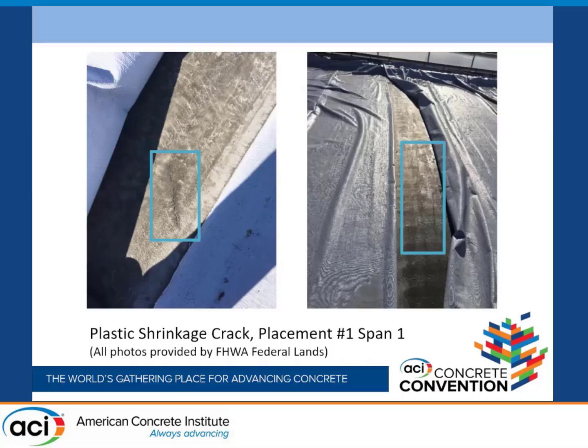There was one incident of plastic shrinkage cracking out of the 13 pours. What happened was, in the very first pour, when they left, the curing mats and polyethylene blew off and exposed a small area. And they did have one shrinkage crack in that area. And of course they started taking more care with their curing mats after that, and they didn't have any other episodes of plastic shrinkage cracks.